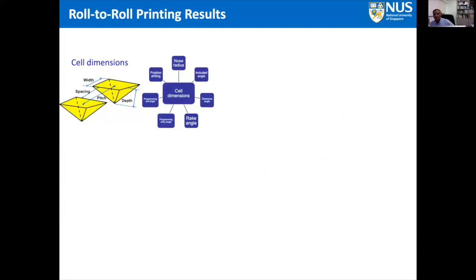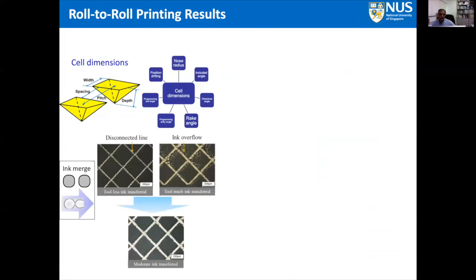So roll-to-roll printing resulted in some problems as well. There is some discontinuity in the printed lines, which is also observed, and that is because of the ink transfer. Also, in some instances, too much ink is transferred, so we still need to optimize this process so that we can achieve better quality features as well.